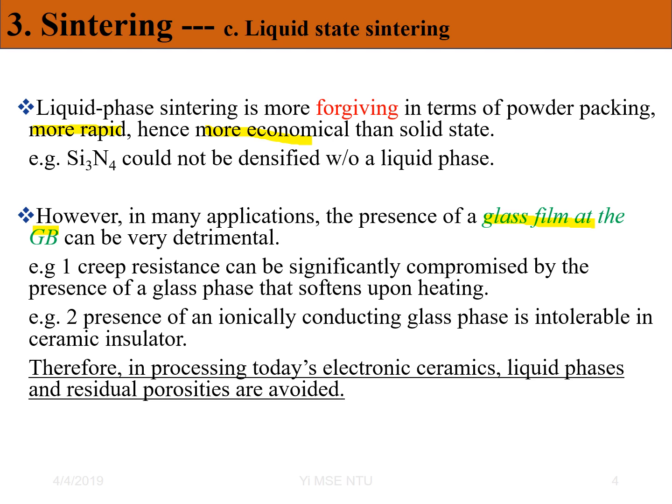As I said, the impurities are more or less like a liquid phase. We call it a sintering aid, and again, it is impurities. So it will never go inside any grains. It will only stay at the grain boundary as a glassy grain boundary. Glassy means amorphous. So this amorphous grain boundary can be very harmful. I give you two examples here.